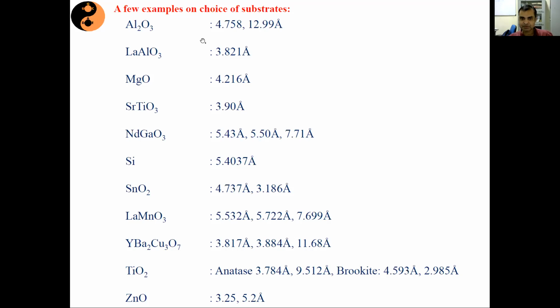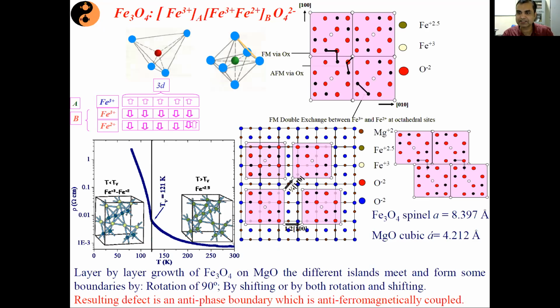Again, for YBCO, I will pick up either strontium titanate or LaAlO3. Now, let me put it this way. If you look at Fe3O4, it has a lattice parameter of 8.4 angstrom. And that 8.4 is exactly double of MgO, which is 4.2. So that means double of the MgO unit cell matches with 1 unit cell of Fe3O4.